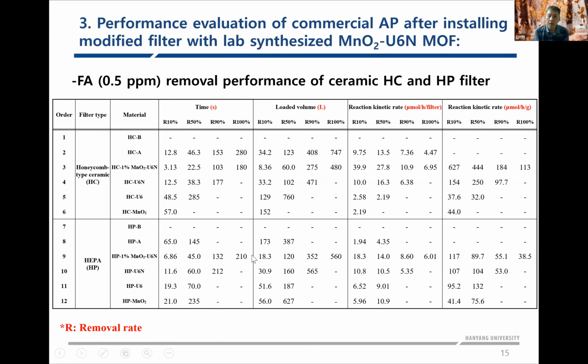Now, most importantly, we tested this system using the honeycomb filter after modification with MnO2 only, and U6, and U6N, and MnO2 U6N. So again, this 1% MnO2 U6N is the ultimate system we developed as a non-photocatalytic system. Even without light on, it can treat formaldehyde.